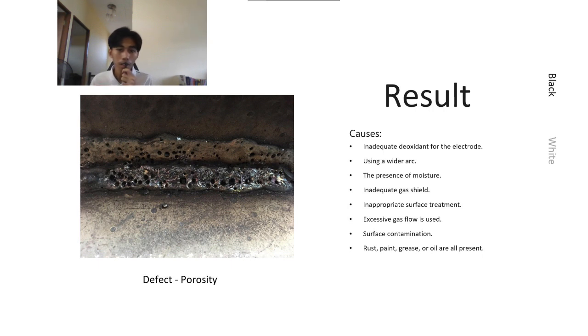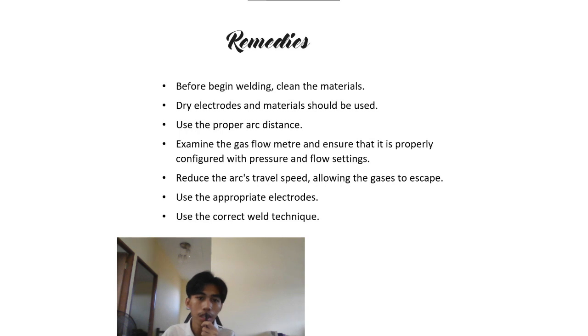Porosity is caused by a variety of factors, including inadequate deoxidant in the electrode, using a wider arc, the presence of moisture, inadequate gas shield, inappropriate surface treatment, excessive gas flow, and surface contamination such as rust, paint, grease, or oil. To prevent this defect from happening, firstly, before we begin welding, clean the materials.